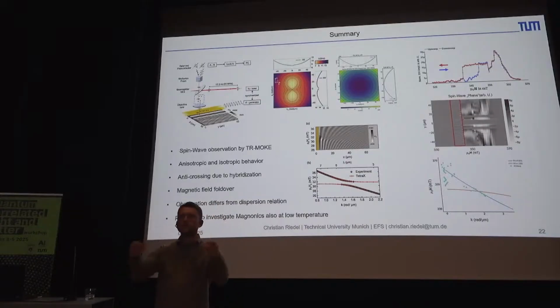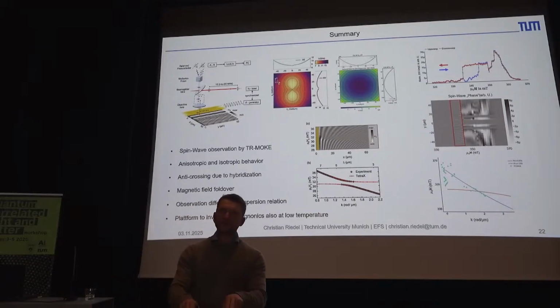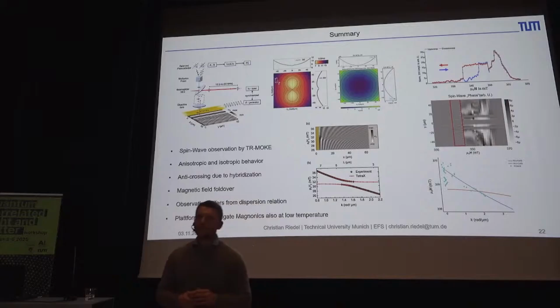Two stripes from it. And with this they actually fabricated a Fabry-Pérot interferometer, because you're changing the dispersion relation inside your material where your spin wave propagates, and with this you always get reflection and transmission ratios. So this border will not be sharp, it will be some kind of adiabatic. It depends on how you change the dispersion.